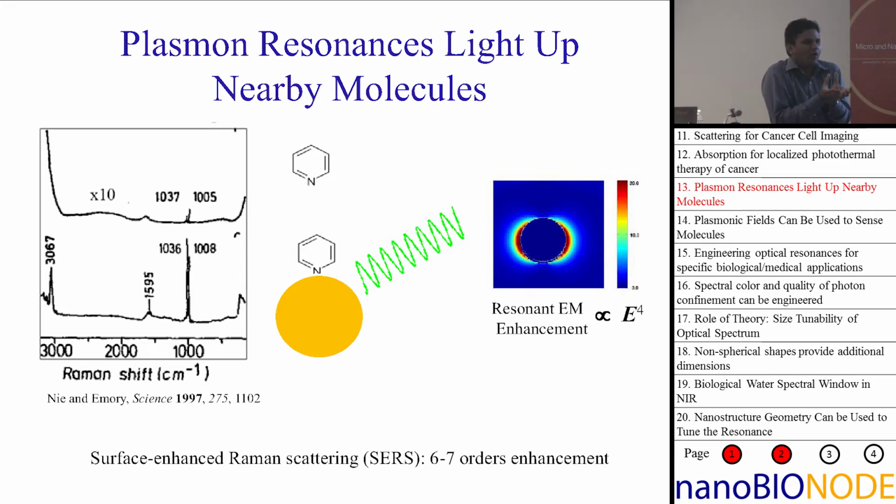This is like a tightly bound spring, okay? And the spring has natural oscillations, right? When you try and compress a spring and you release it, you'll have oscillations. The physics is exactly analogous. When you shine light at the right frequency, which is at the natural frequency of the spring, you can excite these electrons. And the kinds of motions these electrons are having are moving away from each other, closer, back and forth. And so this is a special resonance which is not an interband resonance.